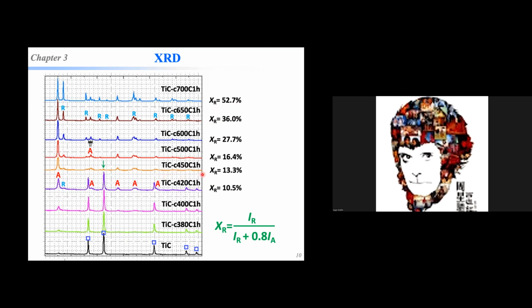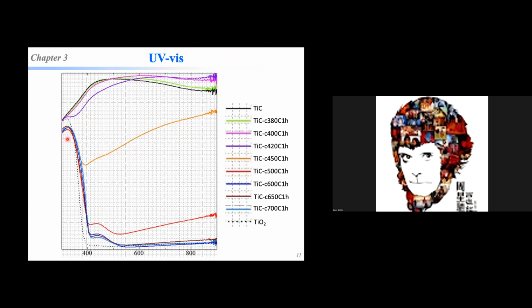When the temperature is lower than 400 degrees C, almost 420 degrees C, the visible response is almost like the TiC. And here shows some kind of response like the TiO2. And with the temperature at 450 degrees C, here shows the typical TiO2 response, and here also keeps something like the TiC or carbon-doped TiO2 response. This is very interesting, and this is very important. It means the core-shell structure can be formed, and with the temperature coming to 500 degrees C, this becomes lower. But here it also means some kind of TiC response maybe.